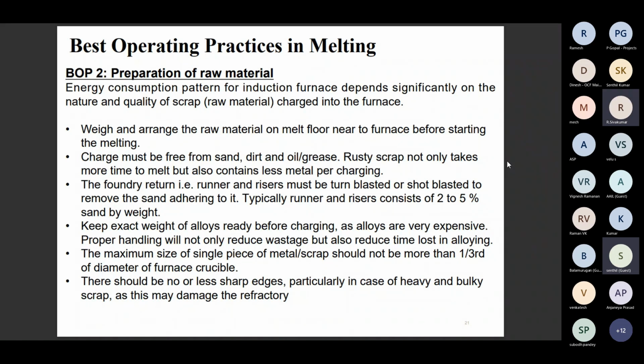The maximum size of a single piece should be less than 1/3 of the diameter of the furnace crucible. Based on capacity, a 500 kg crucible has one dimension and a 750 kg crucible another. The dimension varies based on the diameter of the crucible, and the size of the raw material should be 1/3 accordingly, so minimum less than 1/3. There should be no or fewer sharp edges, particularly in the case of heavy and bulky scrap. Sharp edges damage the refractories, so they should be avoided, and do not throw raw material with sharp edges into the crucible. It damages the crucible.